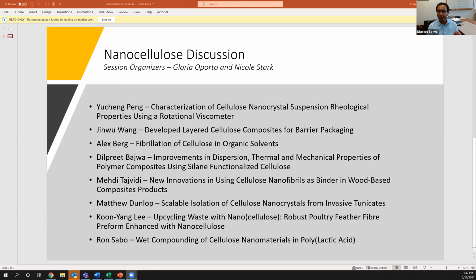And then we picked the dried film out of these Petri dishes, and then we evaluated the properties, looking at both the dispersion of cellulose crystals as well as mechanical properties. And like I said earlier in my presentation, in the two formulations where the silane amount was 2.5 and 5 times the CNC, there were big clumps. We didn't see very good dispersion. Only 1 to 1 was the best dispersion we noted. Did I answer your question?